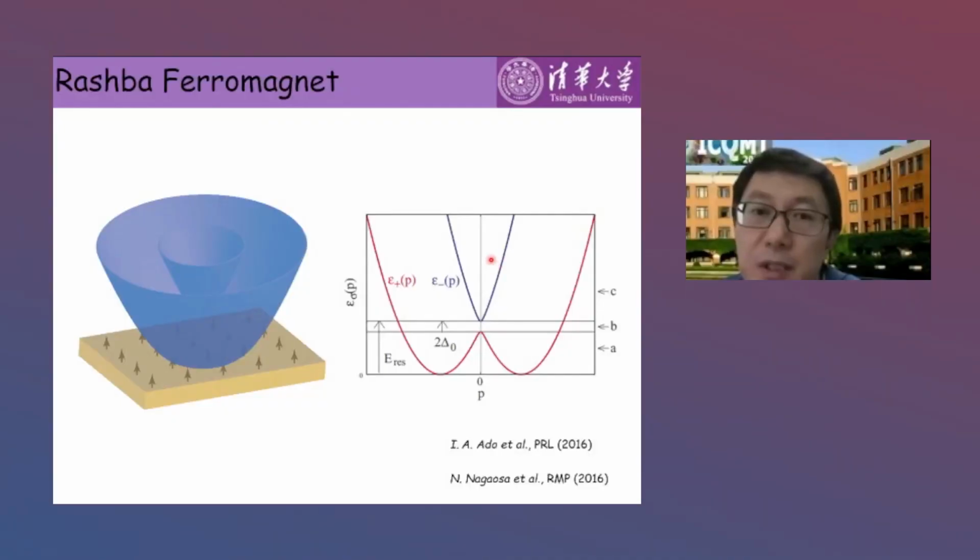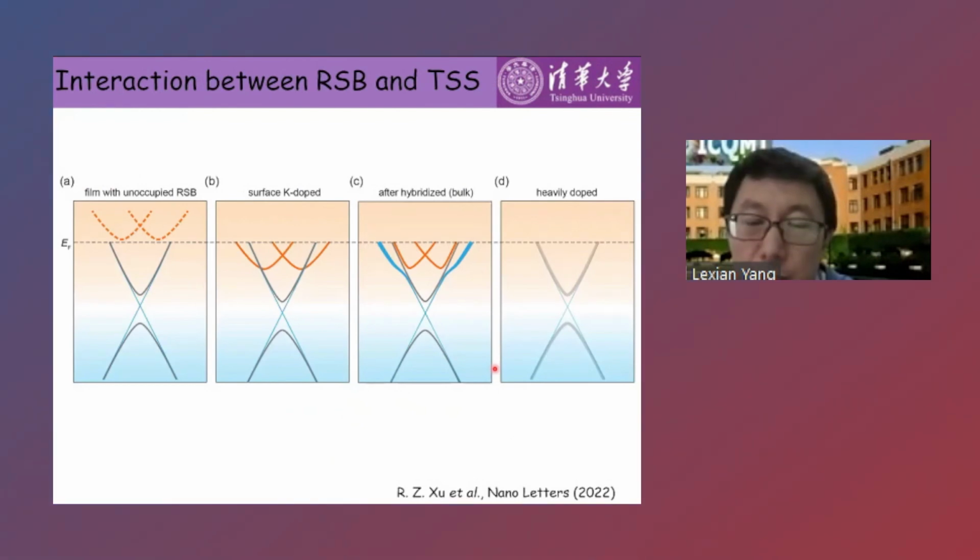Yes, I think a possible reason is due to the defects, which induce additional carriers on the surface. It's similar to the potassium doping. What kind of defects would be different from those that are already present in the bulk? You just cleave the bulk single crystals, and the defects will be there in the surface septuple layer, which would be exposed by the cleavage. The surface is always not ideal. There are manganese bismuth antisite defects which can induce carriers, which can induce the quantum confinement effects. So you think they appear at the surface more than in the bulk? Yes. The bulk layer is a van der Waals material, which is chemically inert and protected.